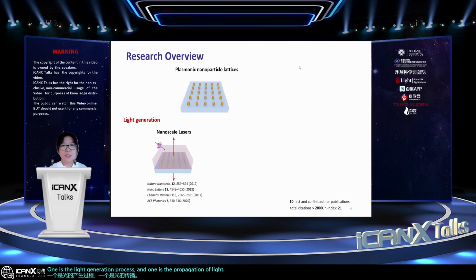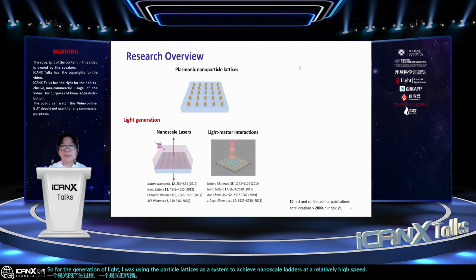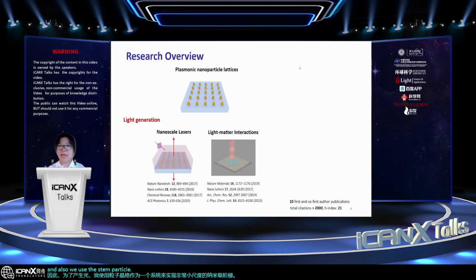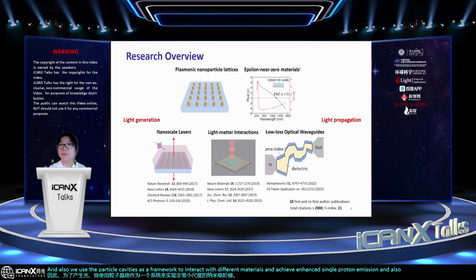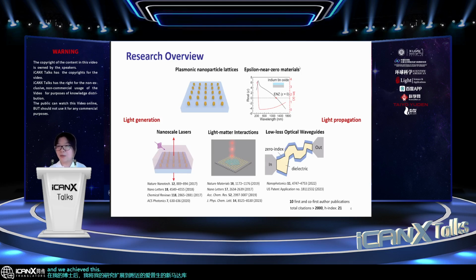For the generation of light, I was using particle lattices as a system to achieve nanoscale lasers at really small scales. We also use these particle cavities as a framework to interact with different materials and achieve enhanced single photon emission and also low threshold nanoscale lasers. Over my postdoc, I expanded my research to new material libraries of epsilon near zero materials, and we achieved low loss subwavelength optical waveguides.